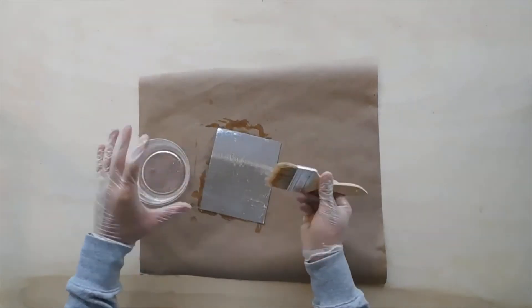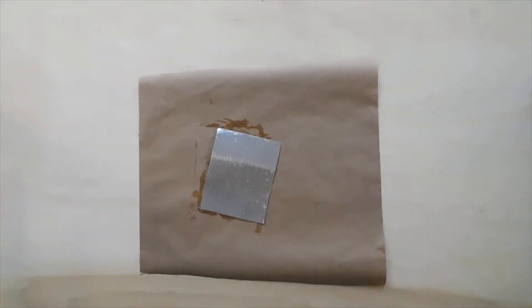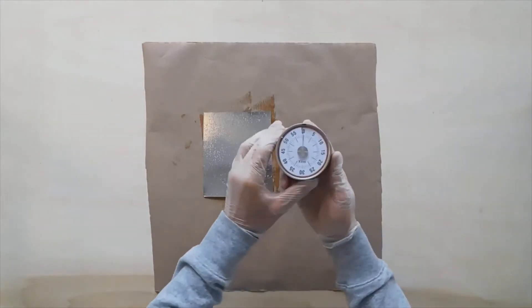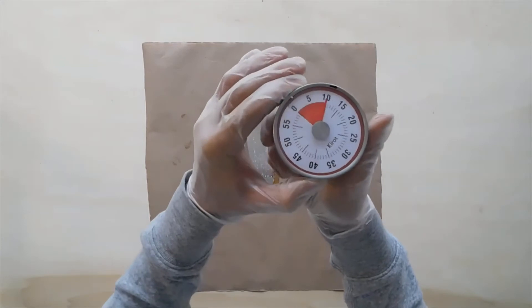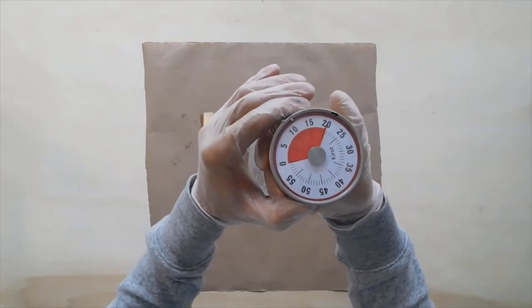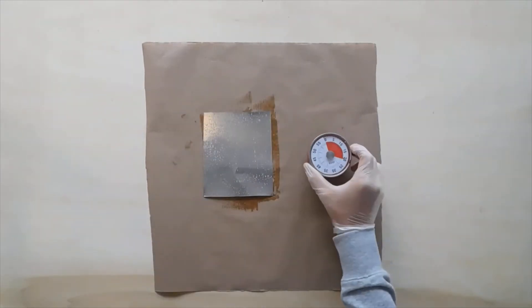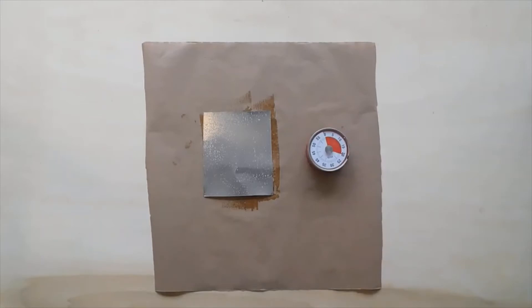Whether you use a roller or brush, before assembling the pieces, you must allow for the solvent in the adhesive to evaporate. This is known as drying time. The length of drying time will depend on the thinner used, adhesive thickness, and temperature. A good starting point is 20 minutes. A heat gun could also be used to speed up drying time.